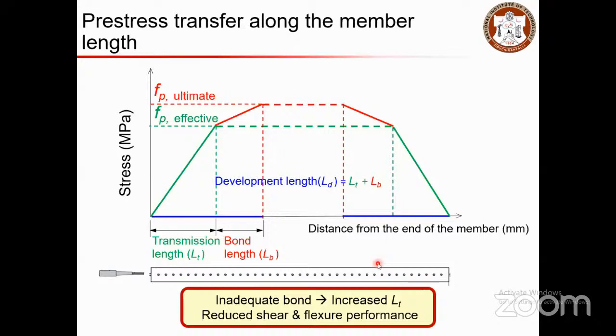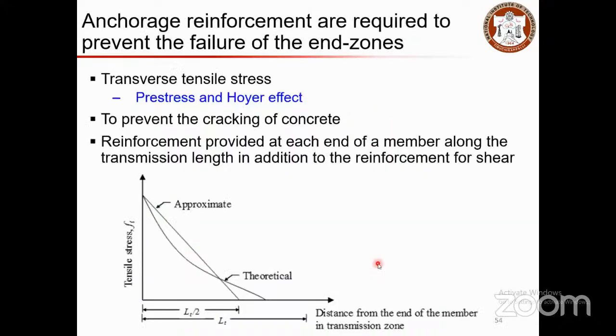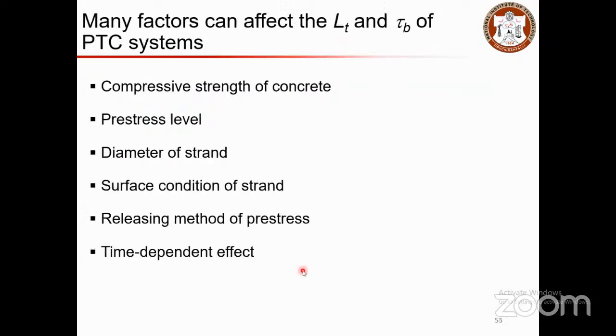Inadequate bond will result in increased transmission length, and when it is increased, that will reduce the shear and flexural performance in the critical regions. Especially at the anchorage, reinforcements are crucial, and that depends on the transmission length of your member. So the major factors that influence the transmission length are the compressive strength of concrete, pre-stress level, diameter of strand, surface condition of strand, releasing methods, and time-dependent effects.